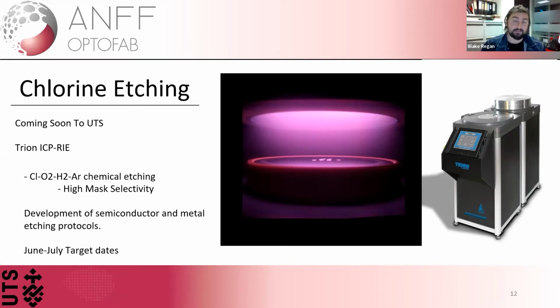We have one SF6-based etcher, which isn't a part of our hub, but it's still one that I'm happy to use on our hub's behalf. And this one will be the chlorine-capable one. So to those of us who are familiar in the semiconductor industry, there are 2 reasons to want chlorine in your etching. Number 1 is for the etching of metals, and number 2 is for the reduction in the effect of micromasking from metallic contamination on the surface. A fairly famous example, at least in my field, was the use of Faraday cages for angled etching, where the introduction of chlorine reduced the effect of micromasking based on its ability to etch away that small amount of aluminium which comes off the surface.